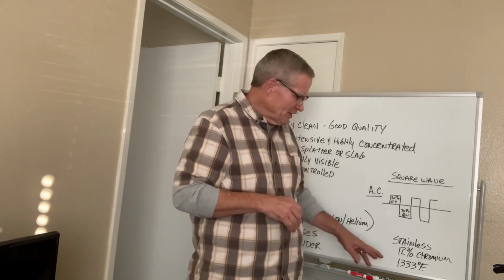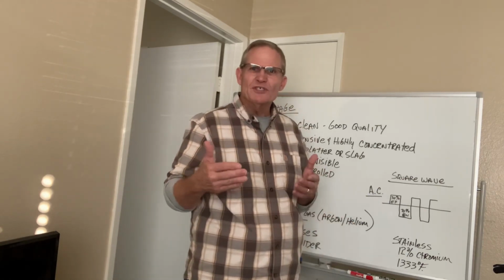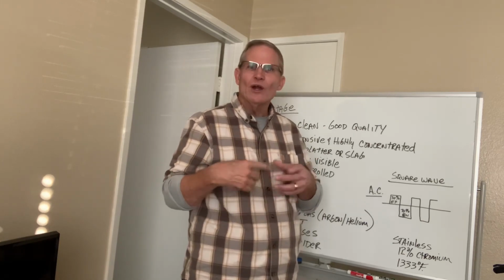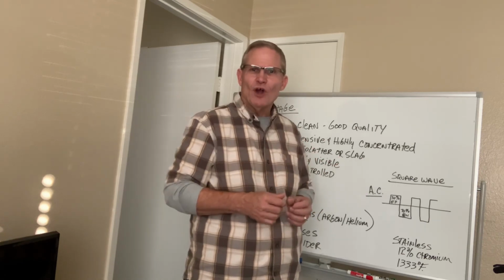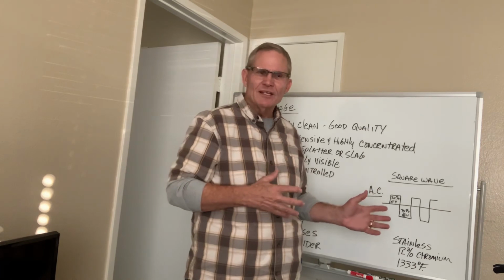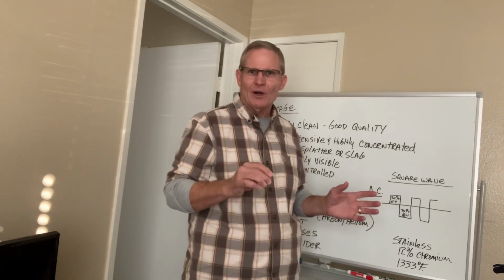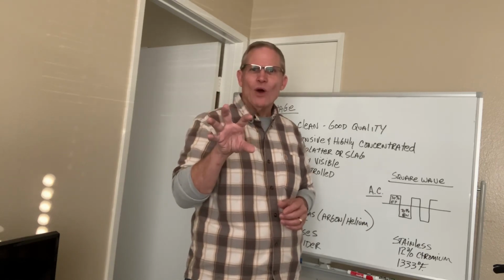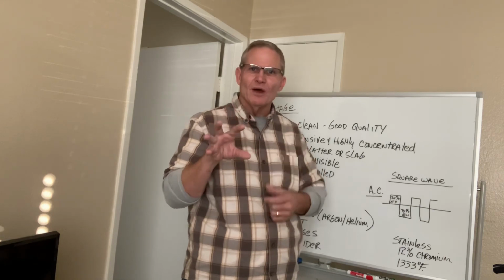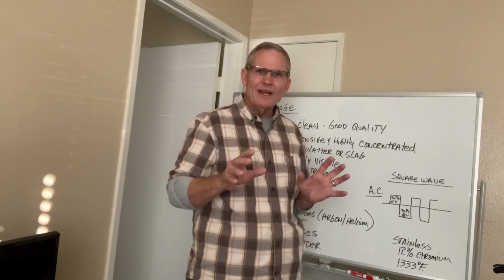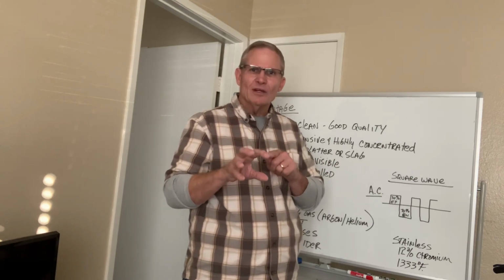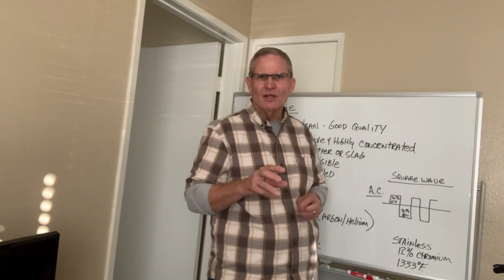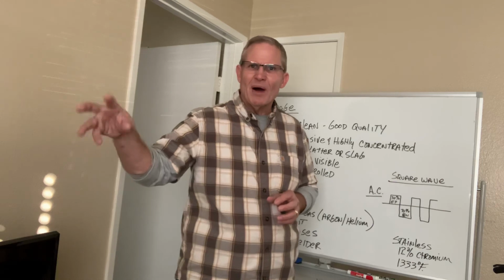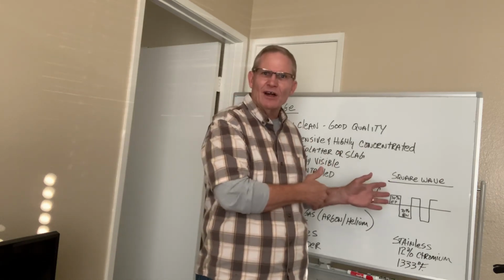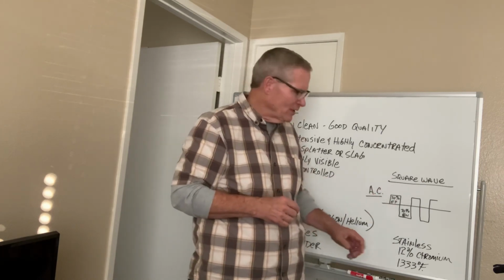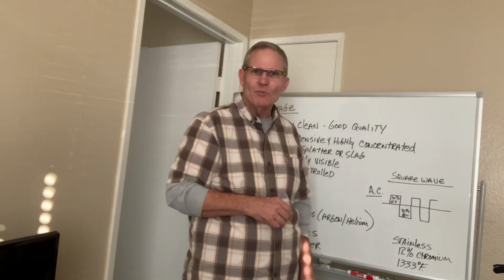Another thing to keep in mind with stainless is you don't want to use carbon steel brushes or carbon steel wire wheels, so that you don't induce more carbon into the weld. So anytime you're welding stainless, we mark everything with a white paint mark. You want to get a stainless steel wire brush and mark it with white paint. Or definitely if you're going to grind, that grinding disc should be marked with white paint so that you're only using it on stainless steel, and not using the same grinding disc on mild steel and then coming over here and grinding the stainless, because you will induce carbon into the weld and increase the possibility of getting chromium carbide.